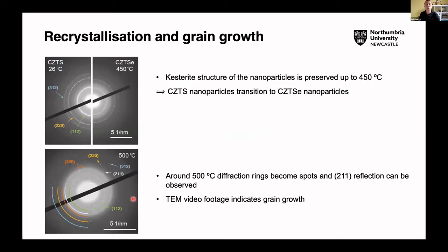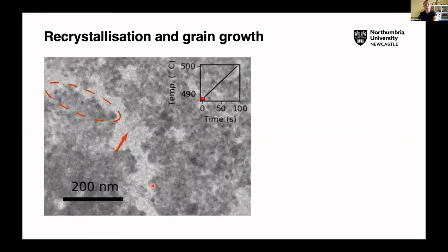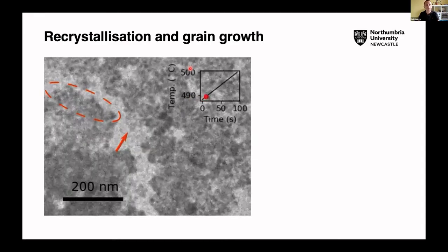And we also see some slight change. The (211) reflection appears now, which might be indicative of increased ordering of the system. And we see some grain growth in the TEM images, and I'll show you that in the next slide. So this is a region of the nanoparticles. What you'll see when I click play is the formation of a grain around the red arrow here in this temperature range, 490 to 500 degrees C. So let's see if that works.